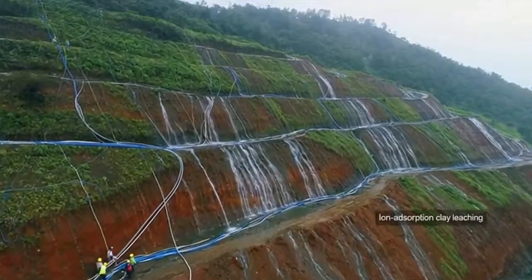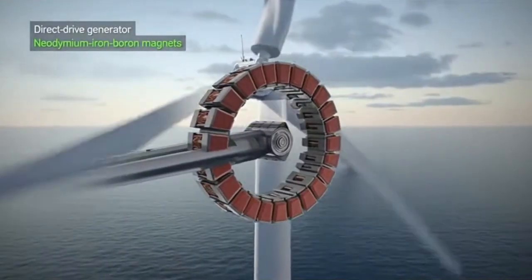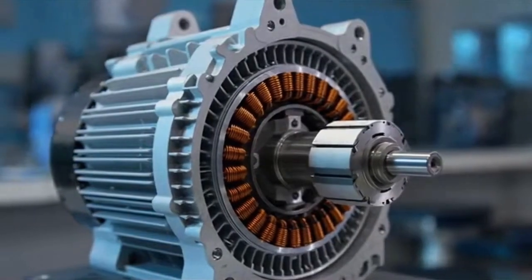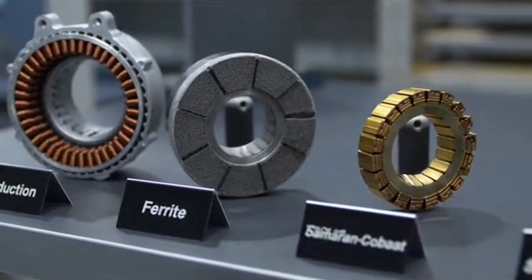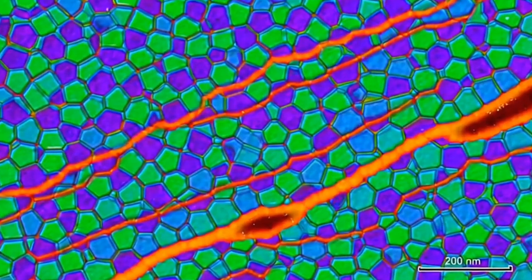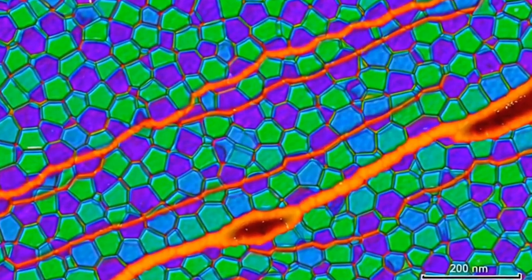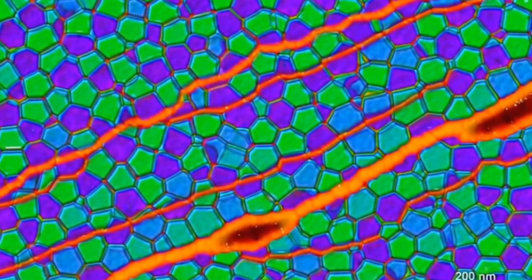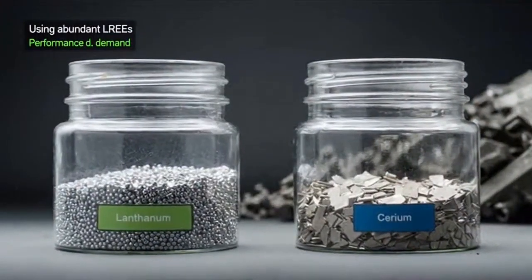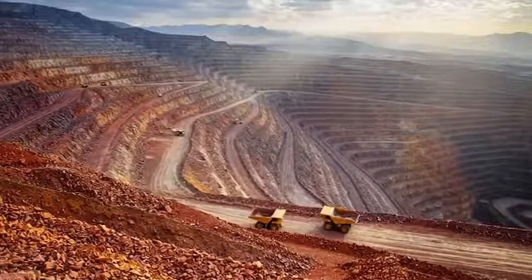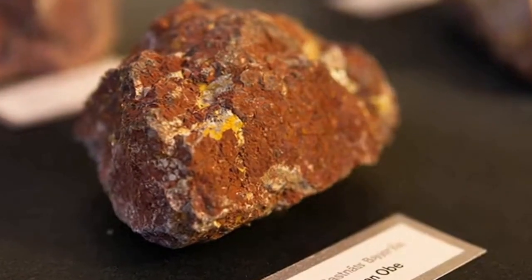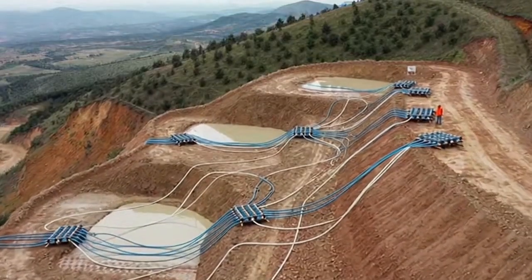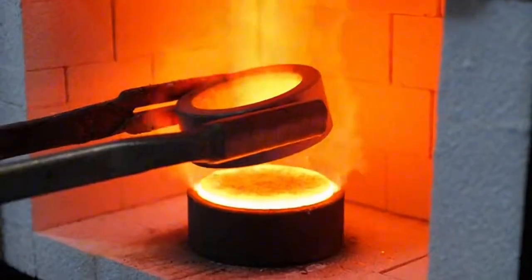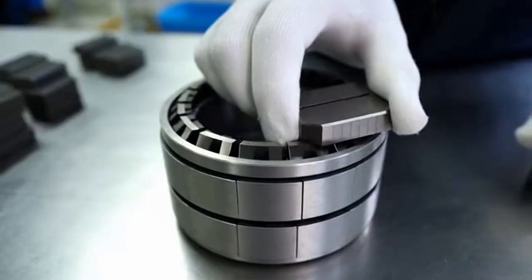Toyota's trick was to accept that magnet performance would suffer if you simply removed some neodymium, and then to counteract those losses through clever materials engineering. They shrank the grain sizes in the magnet to boost its strength, and they used grain boundary diffusion of a small amount of heavy rare earth to maintain coercivity, resistance to demagnetization, despite having less neodymium overall. The public headline for this was, "Magnet uses less neodymium."